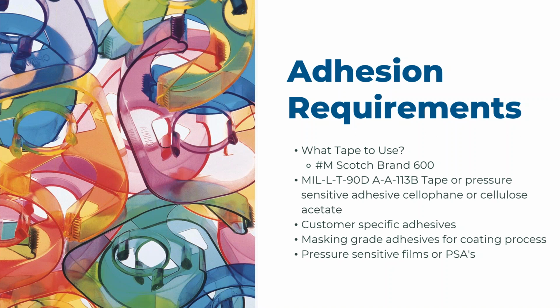Now, this isn't really an adhesion requirement or testing, but again, it could show adhesion issues if you have a pressure sensitive film that removes your coating. So again, just kind of a pitfall and an issue that we've run into in the past.